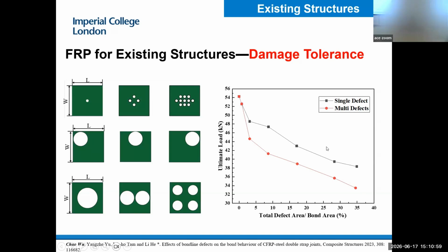The black curve is the strength reduction due to a single defect in the bond line, and the red curve is the strength reduction due to multiple defects. That means if you have multiple defects of the same size as the single defect, you get a greater reduction. That's bad news for this technology.